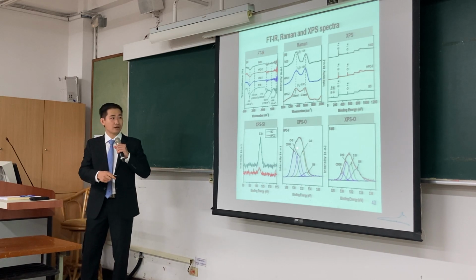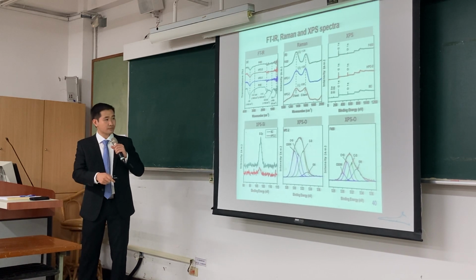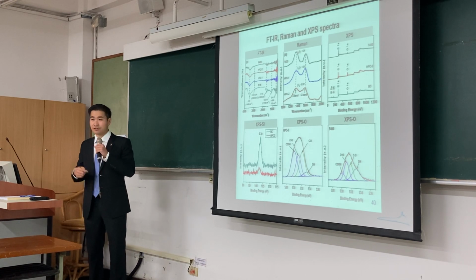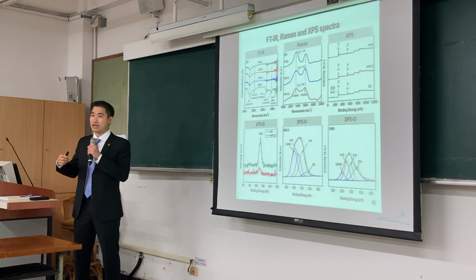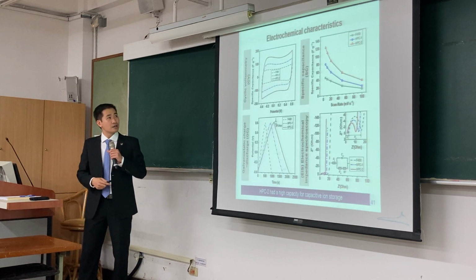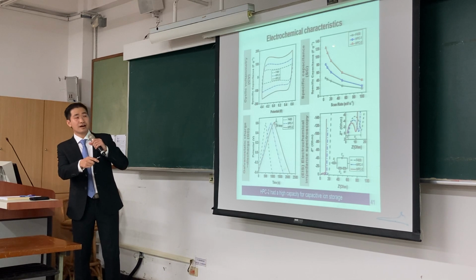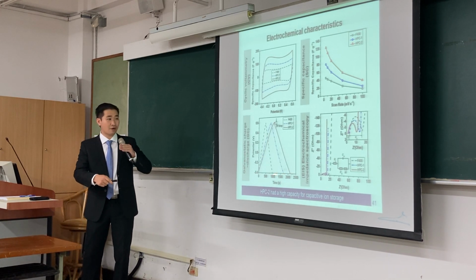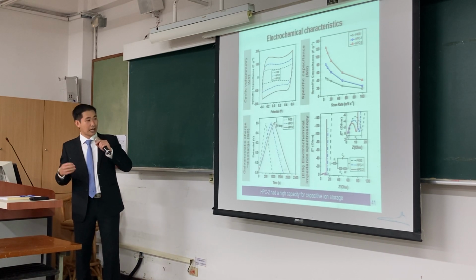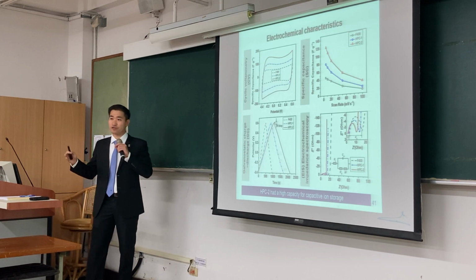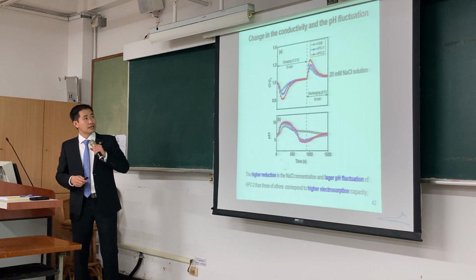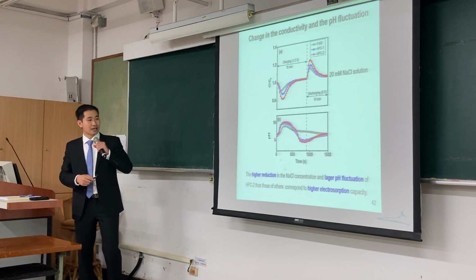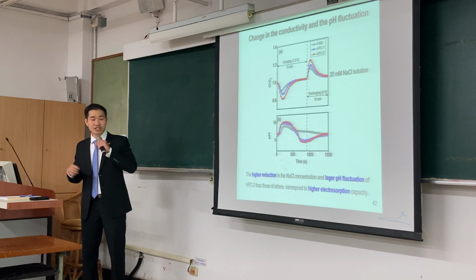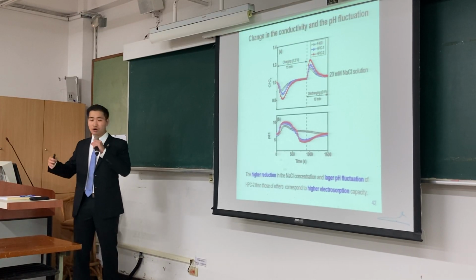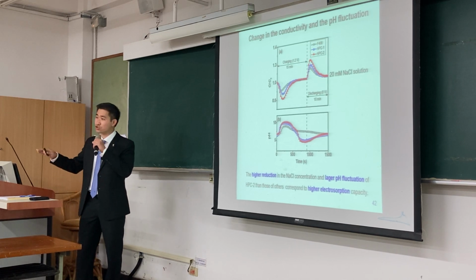More abundant oxygen functional groups on NBC than F100 can be observed. The abundant oxygen functional groups may enhance the reactivity and also the electrochemical properties. A higher specific capacitance, longer discharging time, and lower resistance of NBC can enhance the electro-adsorption performance. And we can see the higher reduction in sodium chloride concentration and larger pH fluctuation of NBC2 than those of the others, corresponding to higher electroadsorption performance.